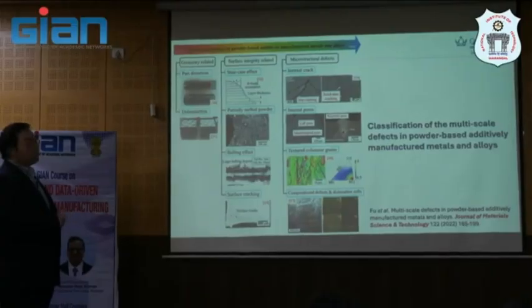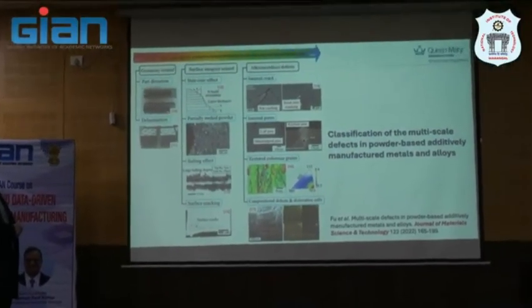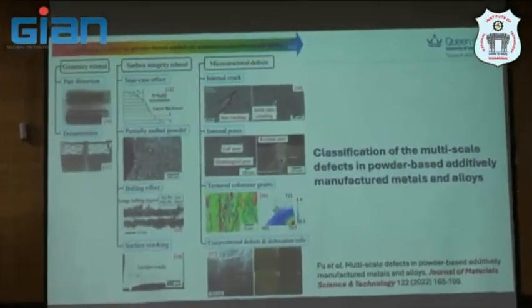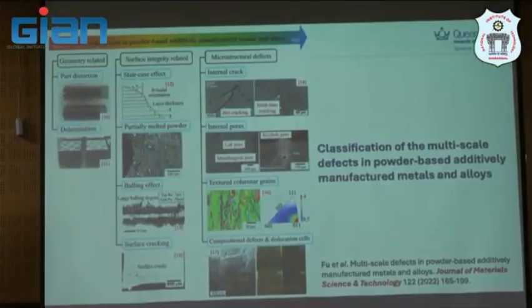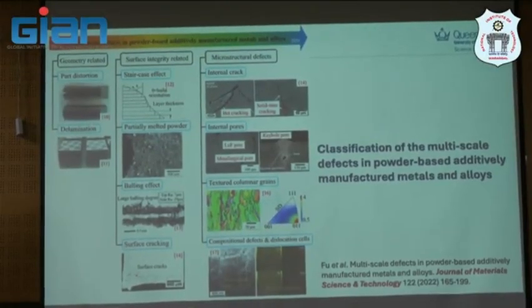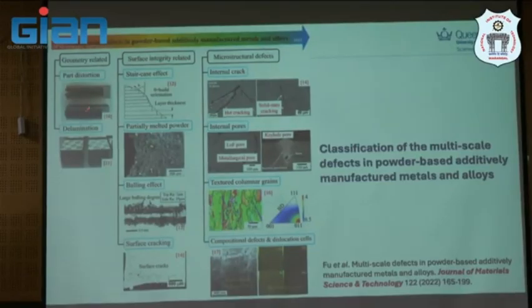One is actually related to geometry, which is a part distortion. So this is a classic kind of cantilever, with this kind of feature. It's actually similar, if you know, to a case study of AM Bench at NIST, the National Lab. This will be a bridge over this with different sizes of the fin here. So delamination is also geometry related, but geometry related is basically because the distortion or residual stress builds